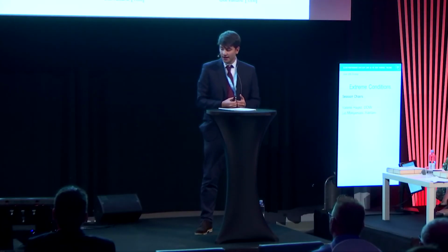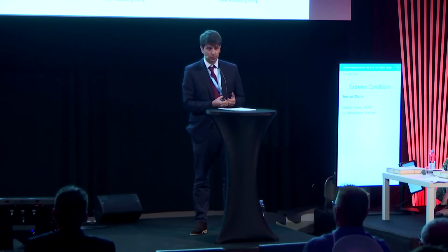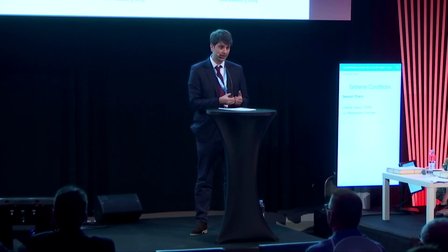An interesting comparison can be made with reinforced concrete, which is also a brittle material that is reinforced with a more ductile material. Bending moment capacities are calculated in an equivalent manner. However, in reinforced concrete, the moment capacities keep increasing with the stages. However, in laminated glass, the moment capacity is decreasing with stages. Therefore, very simple tools such as the upper bound theorem of plasticity that utilizes yield line patterns to design reinforced concrete slabs cannot be applied for laminated glass beams that are actually unrestrained.